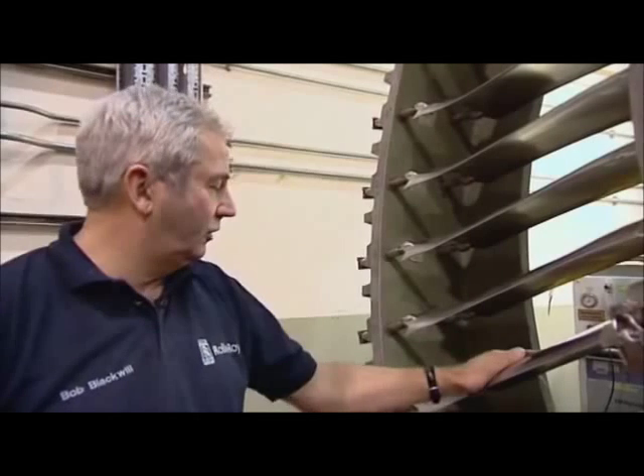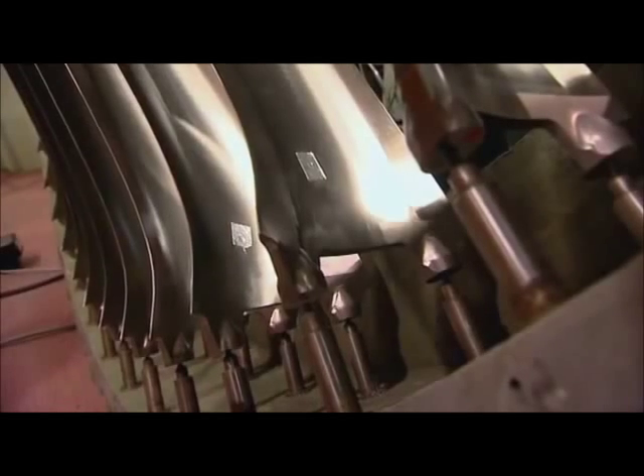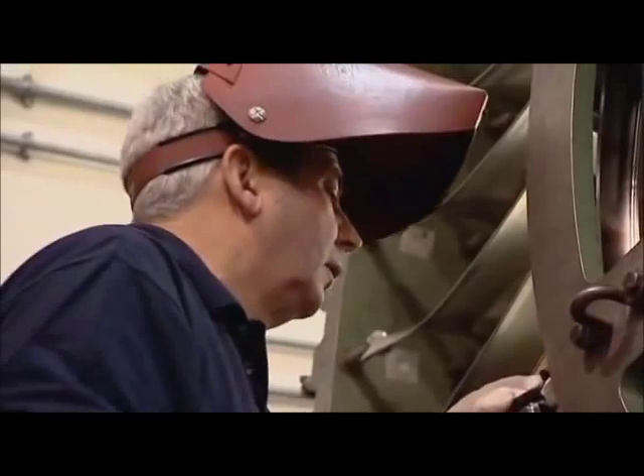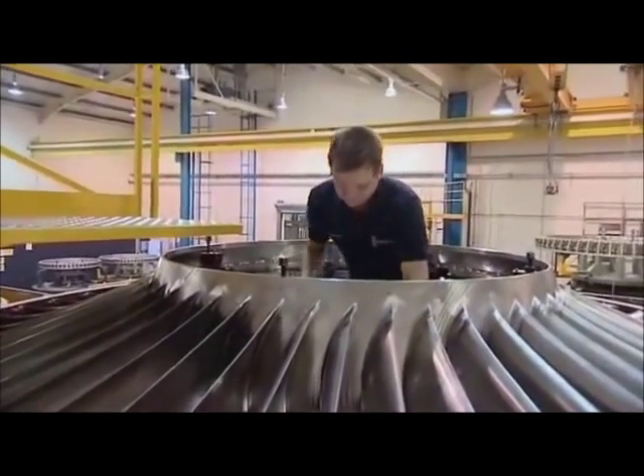When this weld's finished, this vane should leave a tolerance of no more than 5 mil radially and 1 mil forward and rearward on the blade. It's not machined, it's hand skill, and we think that's a fine tolerance to achieve on a hand weld.